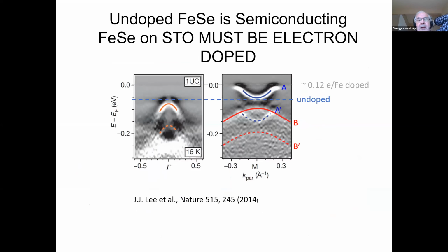Okay. And just going on quickly, we see here, I've now drawn this blue line at the bottom of the superconducting material at the M point, and you see that there is a clear gap between the bottom of that and the top of the hole band, what formerly was a hole band at the gamma point, oppositely dispersing. Okay. And that tells you that this material has to be doped, because you cannot have a non-integer number of electrons just floating around without being compensated. It would have to be charged.